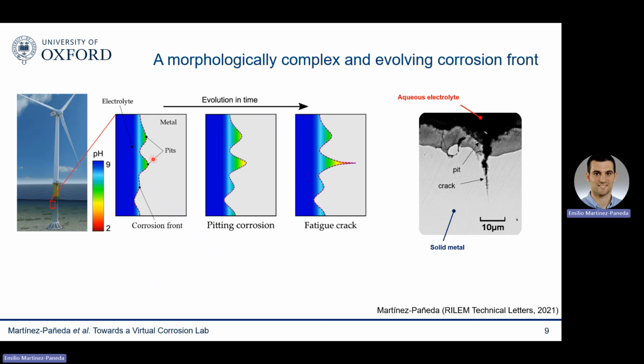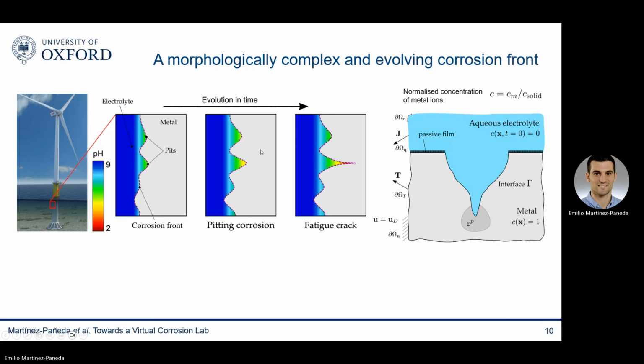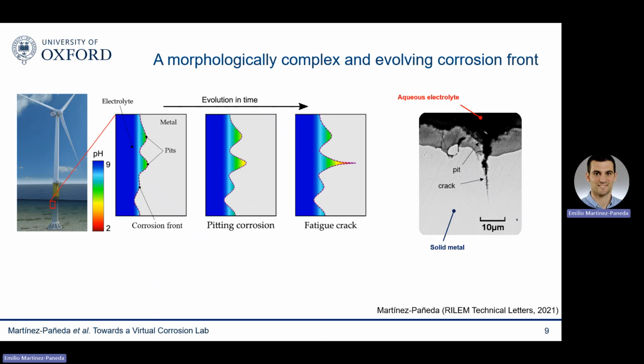So you get an evolution of the pits, then those pits growing, and then eventually this kind of pit to crack transition and the propagation of fatigue cracks. And everything is strongly coupled. The corrosion front evolves driven by local chemistry and mechanics, and the local chemistry and mechanics are themselves dependent on the corrosion front morphology. The stresses are larger ahead of sharper pits, and the pH drops in occluded electrochemistries, as you can see here. So this is the second big challenge, holding back basically the development of physical models.